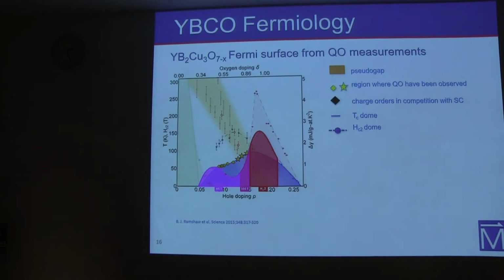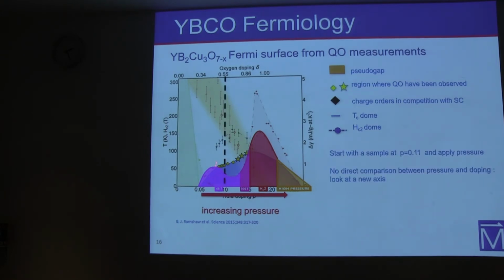So our idea was, not by tuning the doping, but by increasing the pressure and therefore tuning the doping, to look at this overdoped side and try to drive the sample into the overdoped side. So we start with an underdoped sample, somewhere in this low region of the charge density wave. We want to look at the evolution of the charge order and superconductivity with increasing pressure, and at some point, at high enough pressures, look at this part of the phase diagram. The important point that I want to make here is that I don't make a direct comparison between pressure and doping. Pressure will change the doping, but will change also other things. So we're basically looking at a new axis of the phase diagram, but hoping to take a look at what's going on here.